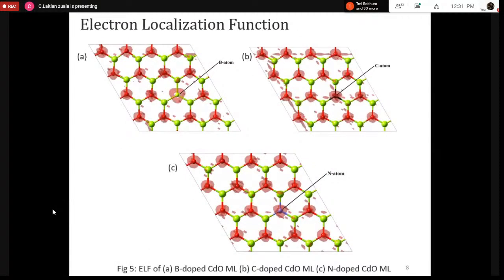Here we have the electron localization function of the boron doped, carbon doped, and nitrogen doped CdO monolayer. We can see that in the case of carbon and nitrogen doping, charges are still localized around the dopant atom or the oxygen atom, which shows that the bonding remains ionic. But in the case of boron, fewer charges are localized around the dopant boron atom, which shows that there is a presence of covalent bonding, but with partial ionicity. Next slide.